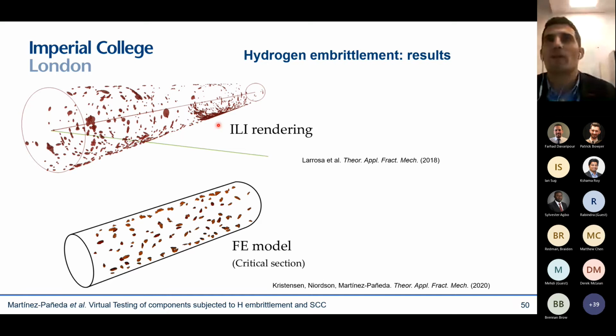What you see here is a 12-kilometer pipeline that has been characterized by La Rosa and co-workers using ILI rendering. What you see here in red are pits. These are pit defects that result from corrosion, and they were able to sample all those pits and their sizes and so on. So we simulate a critical 3-meter section of that pipeline, where most of the defects are accumulated. You can see we have more than 100 of these defects.